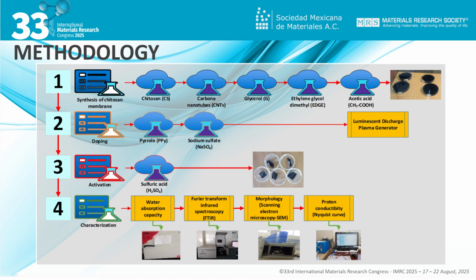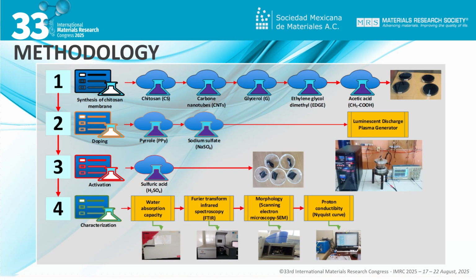Methodology. The synthesis and characterization of the proton exchange membrane, consisting of chitosan, polypyrrole, and carbon nanotubes, was carried out in 4 stages. For the first stage, 3 grams of powdered chitosan were dissolved in 30 ml of deionized water to form a homogeneous solution. At the same time, 2 ml of glycerol were added to 30 ml of deionized water, which was sonicated to homogenize the solution. Once the chitosan and glycerol were dissolved, they were mixed by magnetic stirring for 20 minutes.